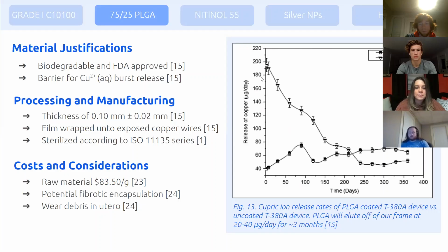The 75-25 PLGA functions like a sieve, where an appropriate amount of copper ions are released from the device to ensure functionality, but not so high that the patient experiences discomfort. The phenomenon of burst release on a control Paragard and a coated Paragard can be seen in Figure 13. After 3 to 6 months, the polymer should undergo complete surface degradation. To ensure this, the 75-25 PLGA will be dissolved in 10% weight by volume ethyl acetate, film wrapped onto the exposed copper surfaces. The polymer will be sterilized using ethylene oxide gas. Additionally, the polymer does present low risks such as fibrotic encapsulation, blocking device efficacy.